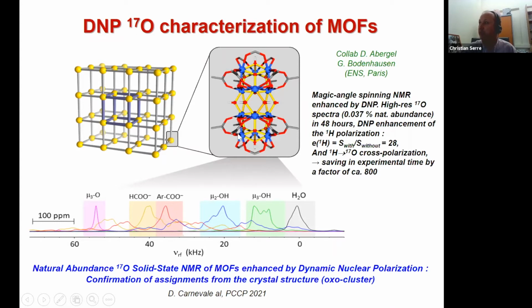So another technique that we decided to apply, in collaboration with a group specialized in DNP NMR, so dynamic nuclear polarization NMR, at ENS in Paris, was to load this mesoporous channel with some radicals. The radicals transfer the polarization to the NMR nucleus. And we wanted to look specifically at oxygen NMR. As you know, only the 17O oxygen nucleus is sensitive, and it has a very, very low natural abundance of less than 0.04%.